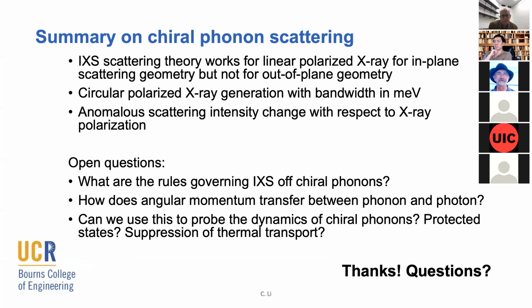Yeah, we are definitely starved for flux. It seems like right now there is not much we can do with circularly polarized X-rays, at least for non-resonant inelastic X-ray scattering, since the intensity is just not there for us to do anything. So any increase in flux would definitely help. And we probably have to work from the ground up in designing the diamond wave plate in a better way that optimizes operation for milli-eV bandwidth. And that might open a new idea of what can be done.